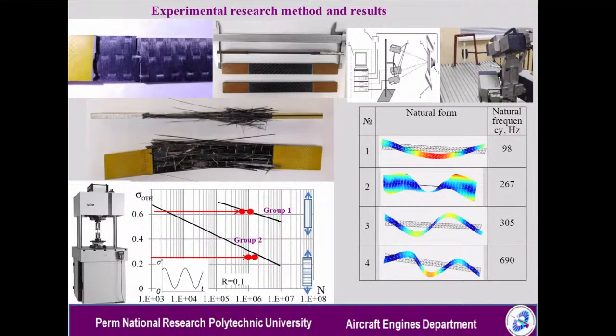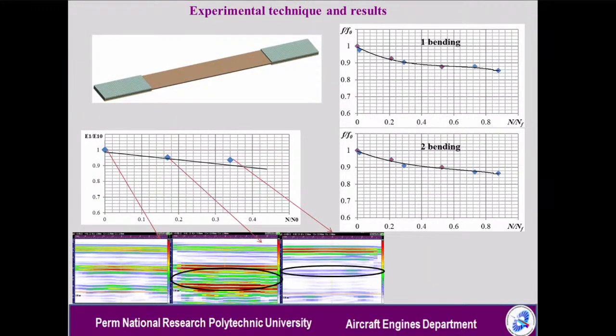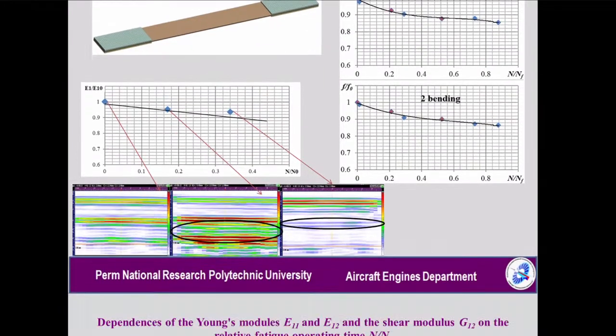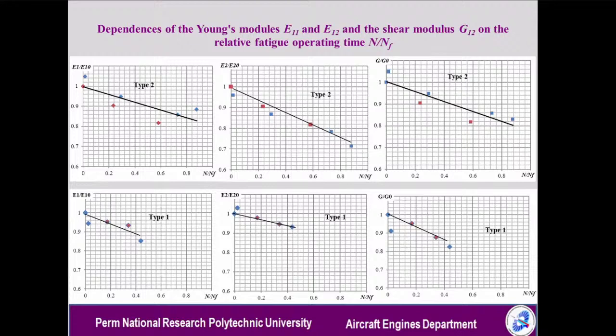The samples were subjected to fatigue tests under cyclic tension with a constant amplitude. Each sample was subjected to fatigue in several stages of cyclic tension, to carry out experimental modal analysis and non-destructive inspection of the appeared defects. The found natural frequencies were used to solve the inverse problem of identifying the elastic parameters of a single layer of the laminate: two Young's moduli, the shear modulus and Poisson's ratio. But we have a few problems with Poisson's ratio. We hope that we can solve that task in the future. That's why now I can show the results only with the Young's modulus and shear modulus.